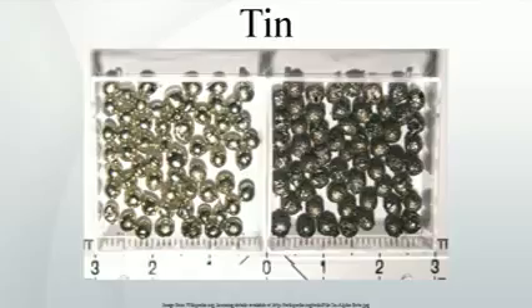Two more allotropes, γ and σ, exist at temperatures above 161 °C, 322 °F, and pressures above several GPa. In cold conditions, β-tin tends to transform spontaneously into α-tin, a phenomenon known as tin pest. Although the α-β transformation temperature is nominally 13.2 °C, 55.8 °F, impurities, for example Al, Zn, etc., lower the transition temperature well below 0 °C, 32 °F.